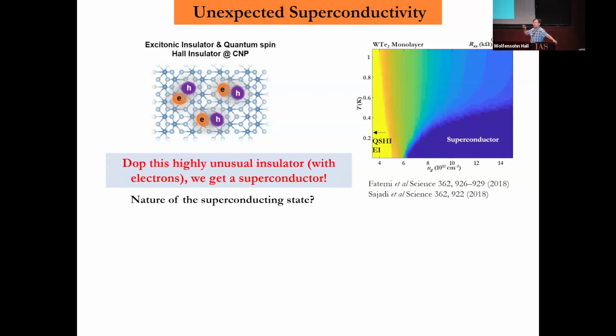Compared to many bulk excitonic insulator candidates, there's a problem of structural transition and real excitonic insulator. Here we don't have that problem because we can do the gate-tuned tunneling measurements. So the case is very strong.